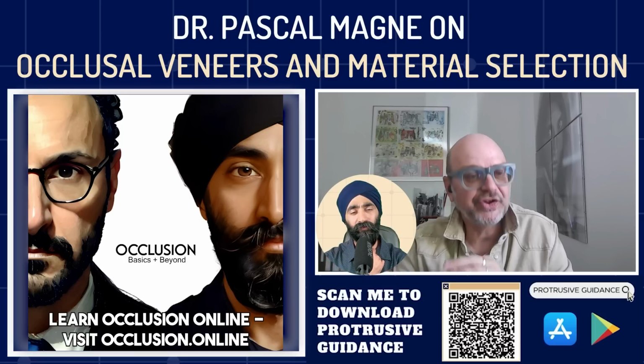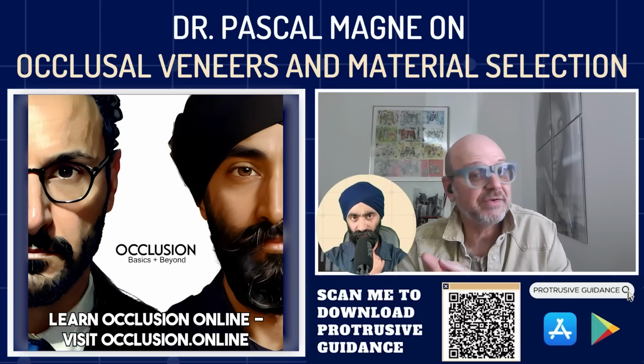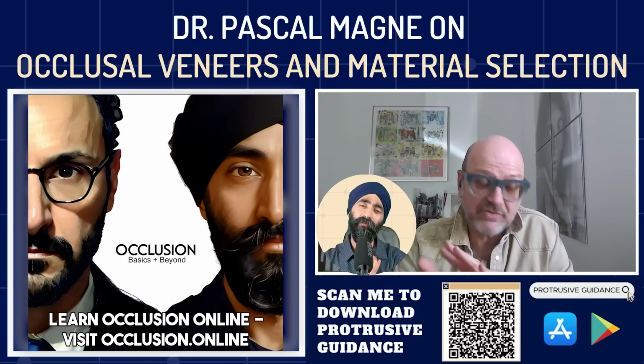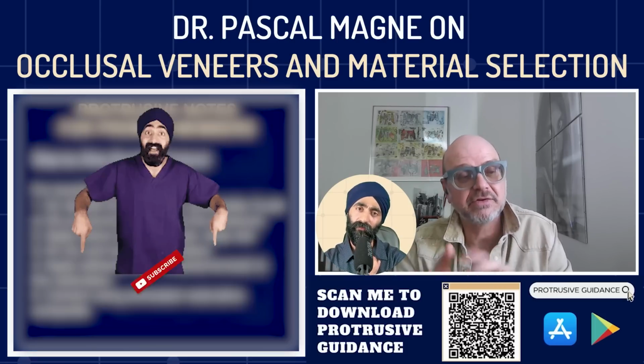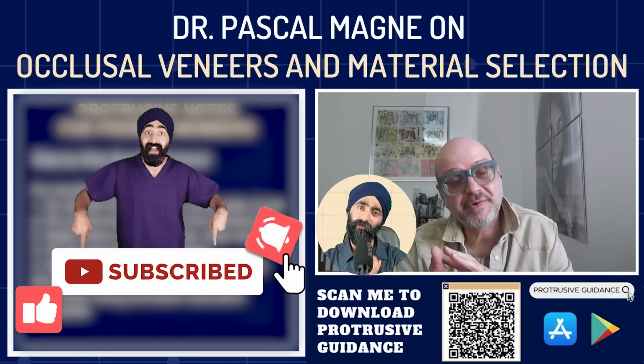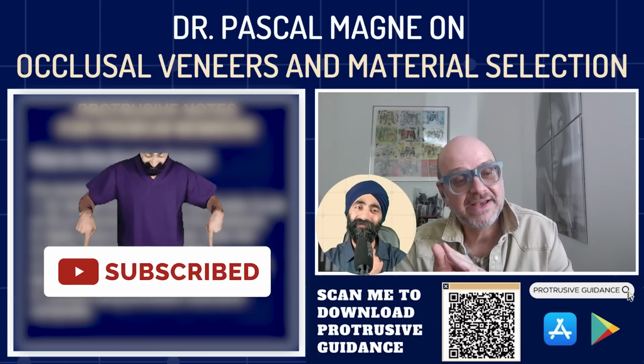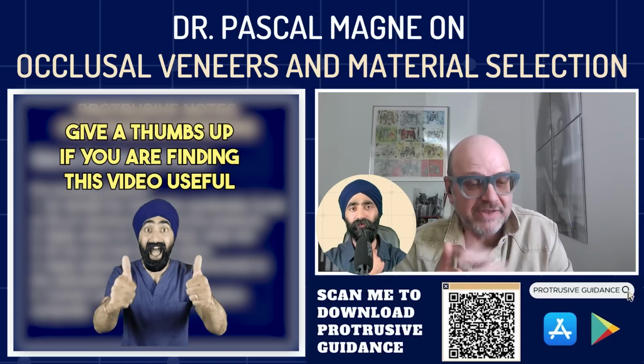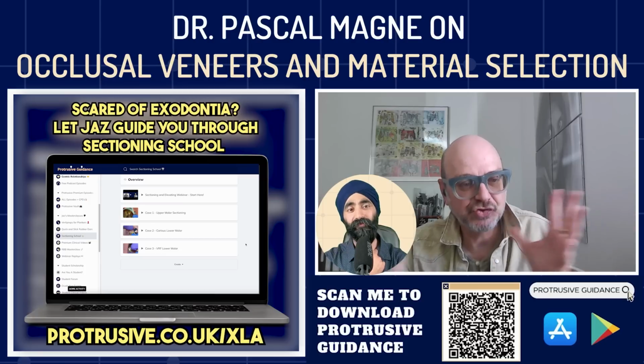And then on the restoration, you do your air abrasion, preferably with CoJet. You can use aluminum oxide, 30 micron, at low pressure, and then CoJet if possible. And then you apply the silane for 30 seconds, air dry, heat dry for 1 minute, and then adhesive resin unpolymerized. And then you use the preheated composite as a cement.